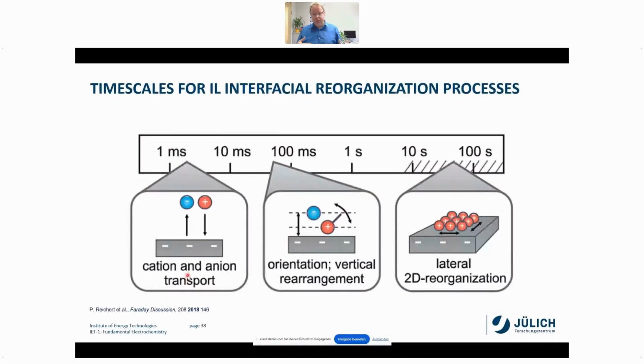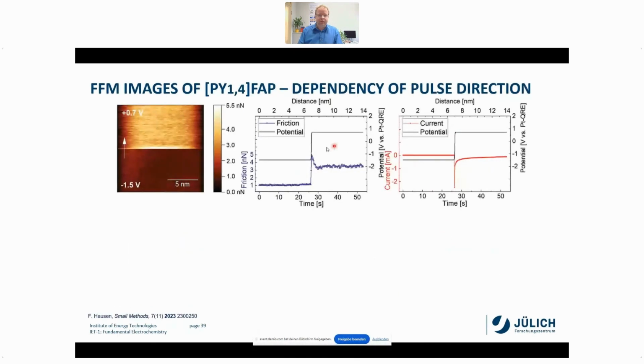It was published quite some time ago that there are different reorganization processes taking place in the order of milliseconds. The cation and anion transport is really fast. Also, the reorientation is in the order of 100 milliseconds. But what is really hard to measure is the lateral 2D reorganization, in the order of many seconds. So we thought lateral 2D reorganization is exactly something we can probe with our friction force microscopy by electrochemical AFM.